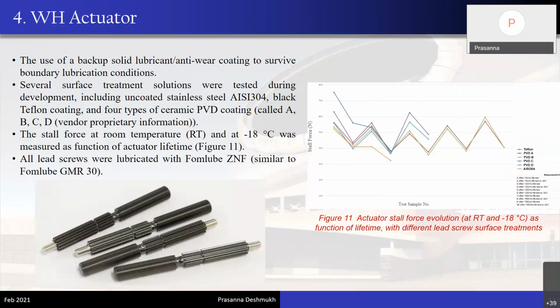Further, as I said, in order to avoid any friction on the lead screw inside the actuator, and to avoid any removal of material during operation, because this operation is very intermittent, every once in an hour we start this operation. So initially there will be a lot of force exerted on the lead threaded part of this lead screw, and hence we wanted to evaluate the performance of lead screws and their coatings. So we came up with different types of coatings on these lead screws. One was just the stainless steel lead screw without any coating. Another one was with a black Teflon coating, and four more coatings were developed using a PVD based coating technique.